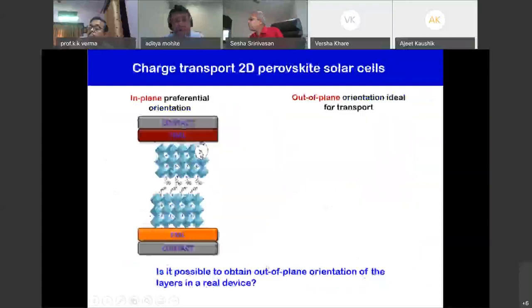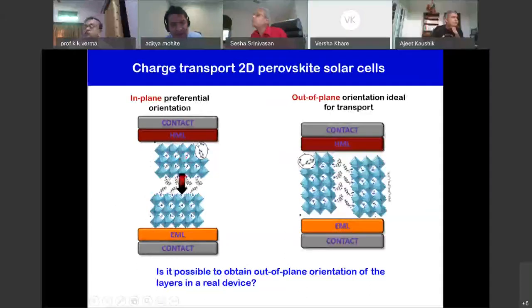And so we realized this quite fast, that if you look at these two-dimensional perovskites, they like to align like this. If you spin coat a film, you have a perovskite slab, and then you have this big organic cation, which is right in the middle. Okay. And so if you're trying to pass a current or measure a device like this, you'll see that the charge is obviously scattered across this insulating barrier, which is this organic cation. And so it would be perfect if you could align this in a 90-degree orientation. So you flip this over and you align it in such a way that your electrons do not scatter away. And so what we set out to do was, can we really achieve this?